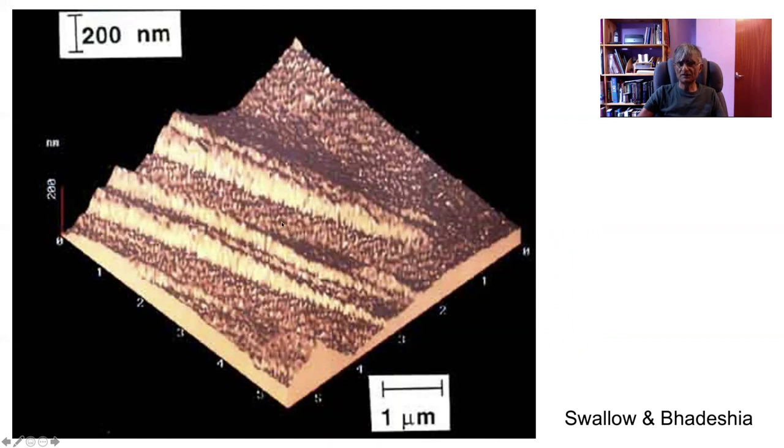This is the austenite, the untransformed austenite. Now, I want you to focus also on this region here, which is austenite, but notice that it has relaxed. It has undergone plastic deformation adjacent to this platelet caused by this large displacement due to bainite formation. And that plastic relaxation happens because the bainite is forming at a temperature where the austenite is mechanically weaker than you would associate with martensite. So it relaxes plastically, and I can show you schematically.